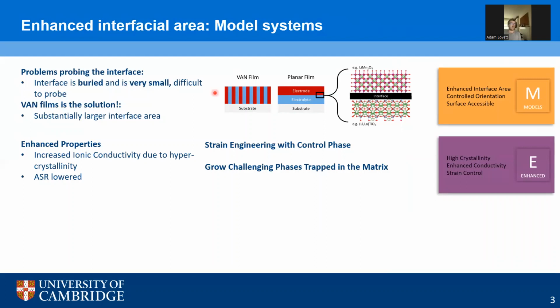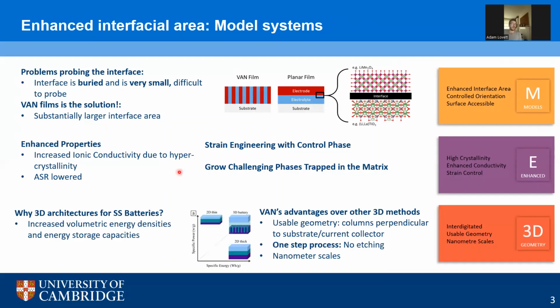Secondly, many of these VAN systems have shown enhanced properties, particularly enhanced ionic conductivity due to hypercrystallinity. Also lowered area-specific surface resistance, which is important to getting a good performing battery. We can also play around with strain engineering to tune the physical properties of our material. And we can also stabilize challenging phases by using the matrix as a scaffold to support columns of a difficult phase to grow. And finally, VAN films are an example of a 3D battery architecture, a very hot topic in the field at the moment. This may allow us to get increased volumetric energy densities and energy storage capacities.